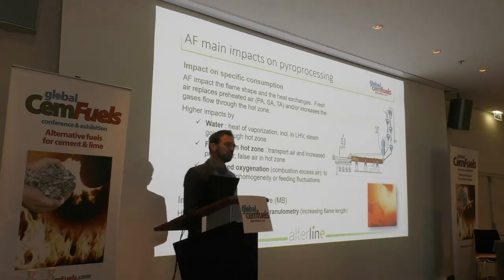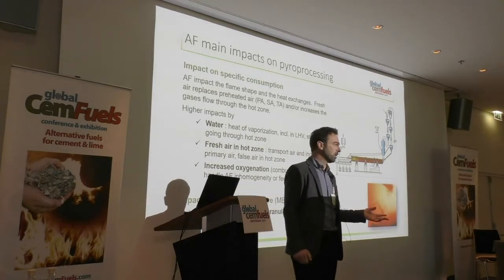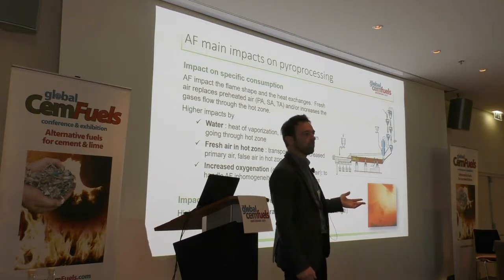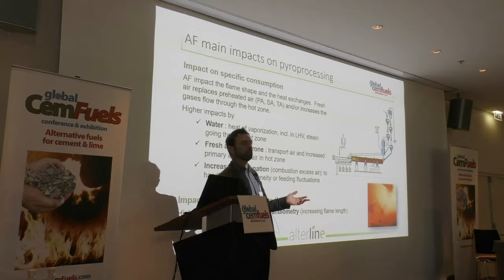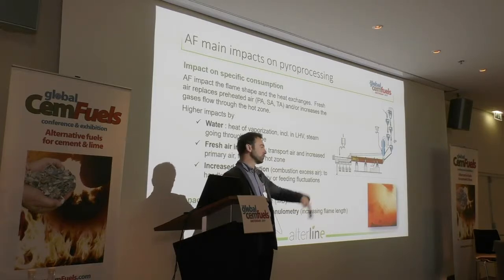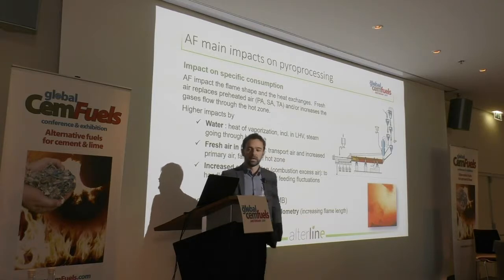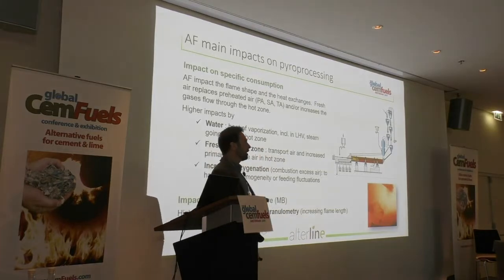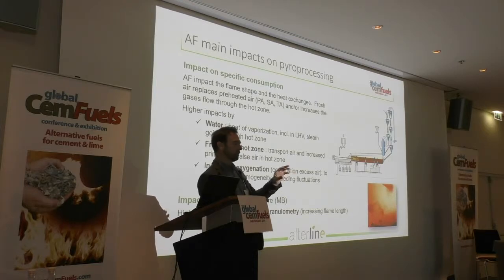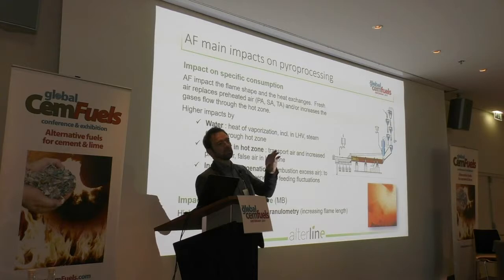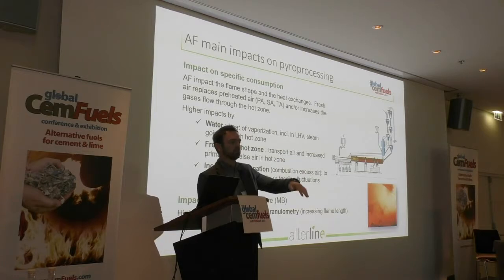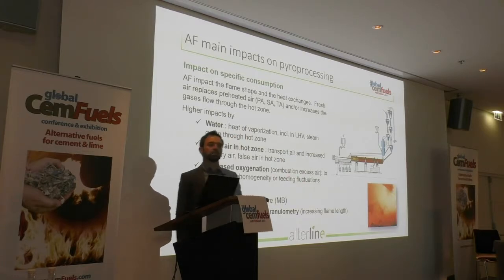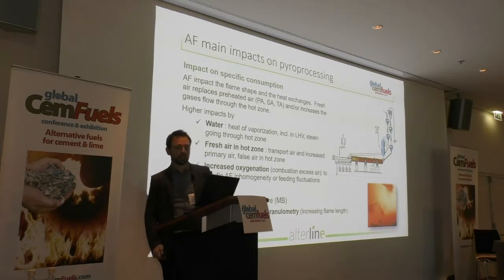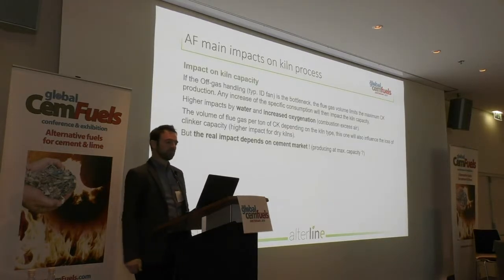The impact on the flame temperature, of course, depends on the kiln. If you have a short kiln with 40% thermal input at the main burner, the impact will be much faster than if you have a long wet kiln with a huge consumption and only the main burner. The problem is typically linked to the water content and to the particle size, because if you have big particles, you will increase the flame length to avoid the particles falling in the bed, and then you can have too low flame temperature, among other problems. The kiln capacity, the impact on the kiln capacity.